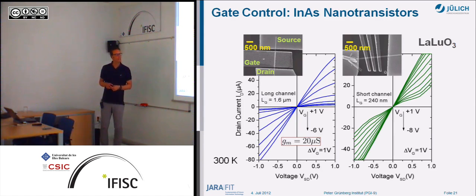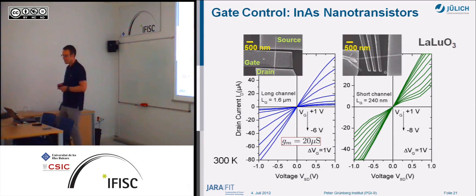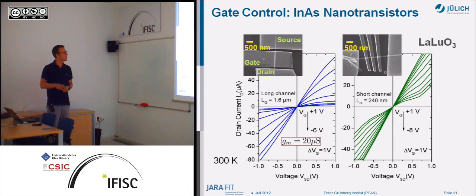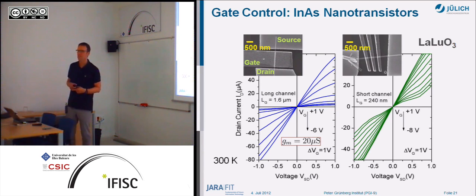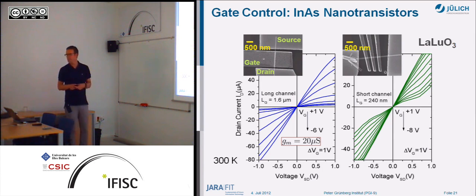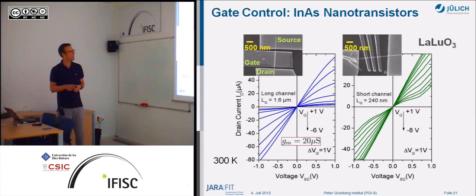And you can see here, these are typical examples for transistor structures. So this is the source drain voltage here, the drain current. But here we change the gate voltage, so you see that you have a nice transistor action here. So that's a gate here which is controlling the conductance of the nanowire here. And we can do the same for shorter gates here. So you have short channel effects you see here.